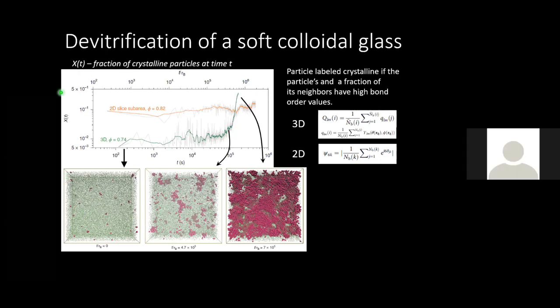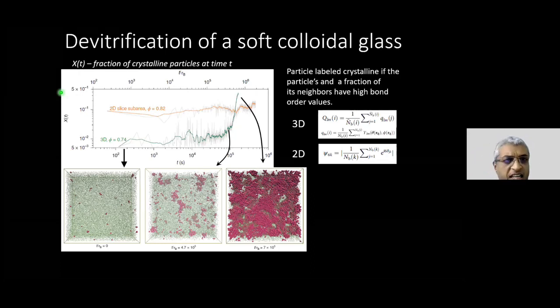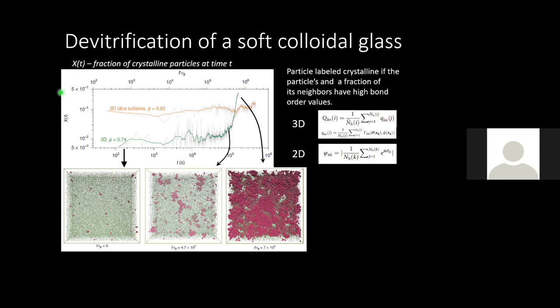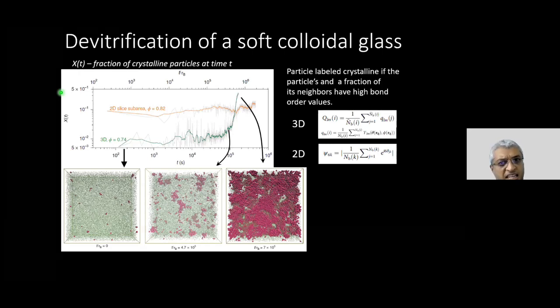Rajesh, just a question. So these are room temperature experiments? Yeah, these are colloids, Shubhro. So what I'm controlling really is, once I freeze the system at say 0.74 volume fraction, I'm just going to watch it as a function of time, and these are done at room temperature. Okay. And there is no substantial temperature dependence, like if you heat it to boiling point or something, these results do not change substantially? So these being a colloidal suspension, the only parameter that we have to worry about is how many particles we can pack in a given volume. Of course, these are in water, so you don't get to play around with temperature more than a given range, but we are at room temperature.